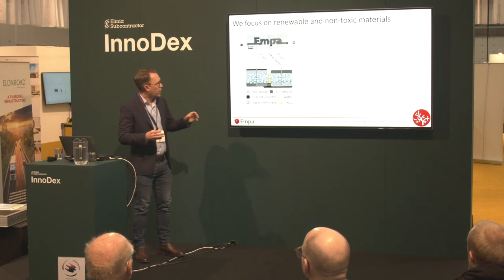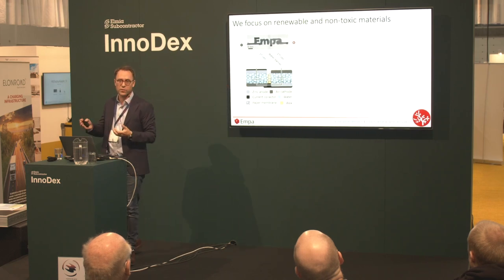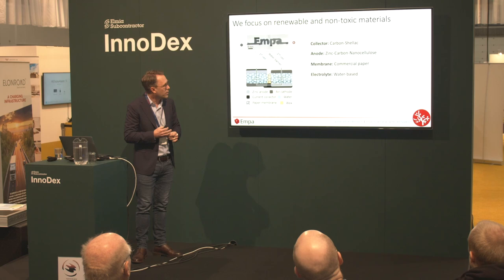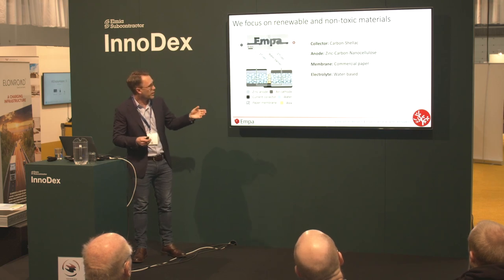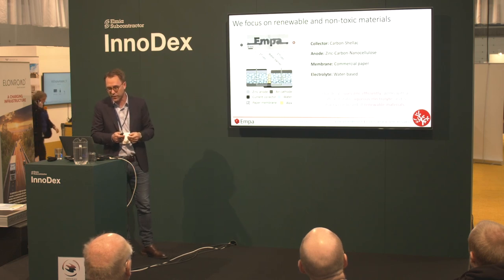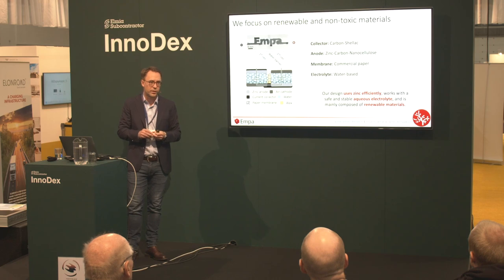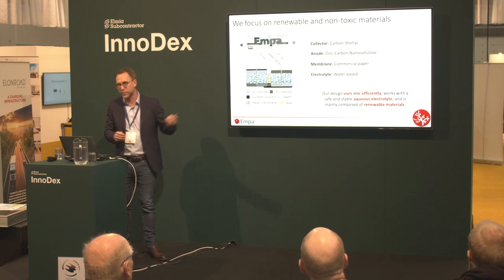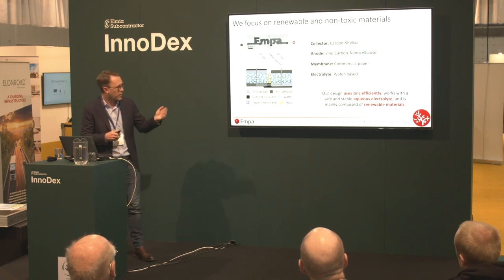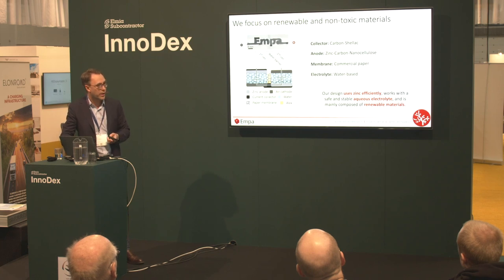You can also couple many of these cells together to increase the operational voltage of the device. The membrane is simply commercial paper, there are two ink systems for the two electrodes, and the electrolyte is water-based. We think printing is advantageous here because we can precisely control how much zinc is deposited, whereas conventional zinc-foil batteries make it harder to control the amount of metallic zinc used — so printing offers a sustainability advantage by tuning charge capacity precisely.